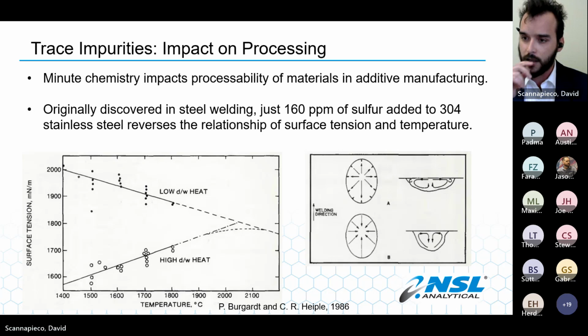And so now your powder might change how it's able to be processed without you changing parameters to compensate for it. You end up with bad parts after some amount of time. Who knows how long it might take to absorb 160 ppm of sulfur.